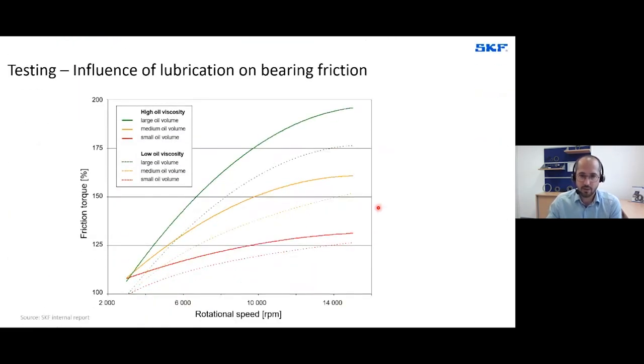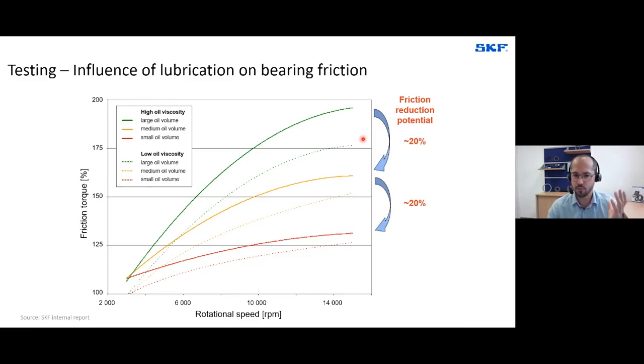And again, we carried out tests. We did a lot of friction torque measurements on different lubrication conditions. Here you can see the solid lines, which represent the high viscosity oil, and the dotted lines, which represent low viscosity oils. And the different colors indicate different oil volumes. So if you change your oil volumes or reduce your oil volumes, you can already substantially reduce the friction inside your bearing arrangement. And you can even give it a further boost if you optimize the viscosity.